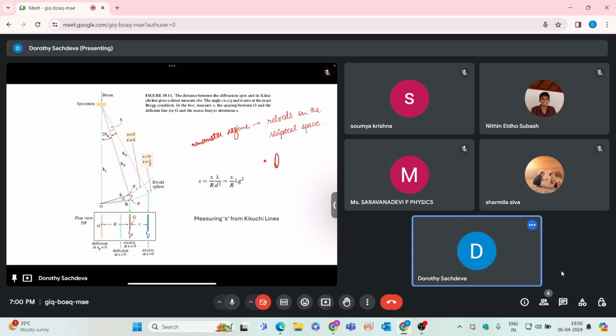Okay, so these are the relrods, and we said that the Bragg condition will be followed only when your Ewald sphere passes through this diffracted spot. So if your Ewald sphere is like this, then your diffraction spot is now passing through this Ewald sphere. That means it is following Bragg's condition. That means it will be diffracted. But if your Ewald sphere is like this dotted one, then you can see that your single diffracted spot is not touching, but the relrod is touching.